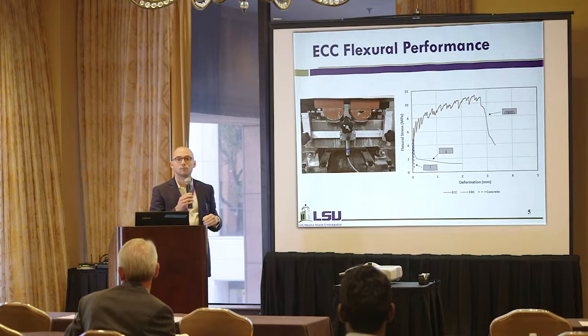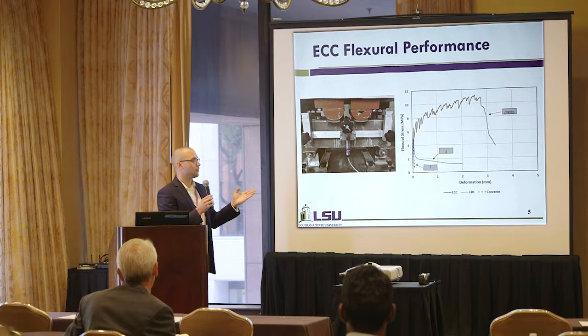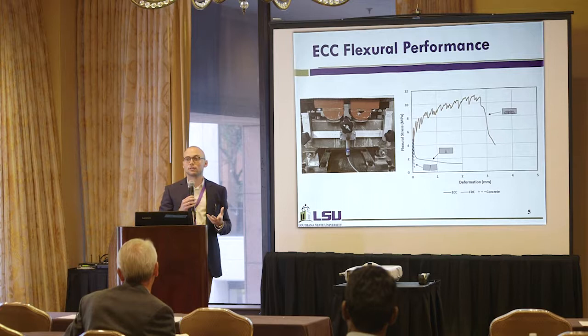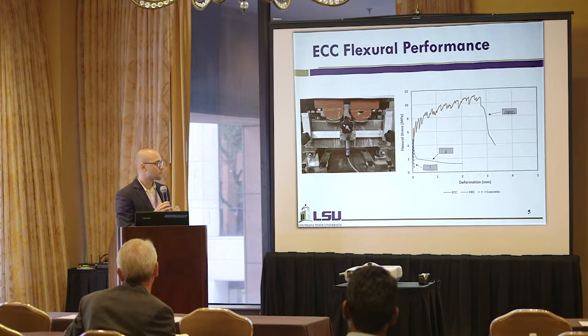What are the implications of this? First and most importantly, you have a much higher modulus of rupture — about two to three times that of typical concrete. Furthermore, the area under this curve is the energy of deformation, which has been related to increasing load carrying capacity of slabs on ground. So there are many potential benefits for the design of pavement with these materials.